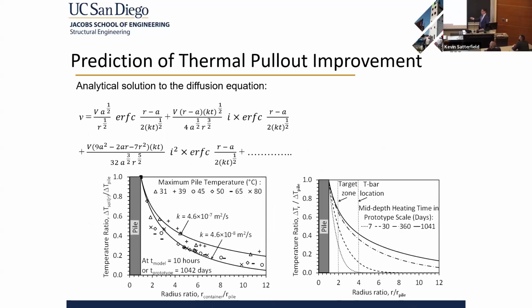So then we needed to predict the change in temperature of the soil around the pile. So we used an analytical solution to the heat conduction equation and obtained these different profiles. We wanted to heat the soil within a target zone around the pile that was going to be affecting the capacity. Our T-bar location is located outside of that target zone, but if we see improvement at the T-bar location, it means that we're also having improvement near the target zone.